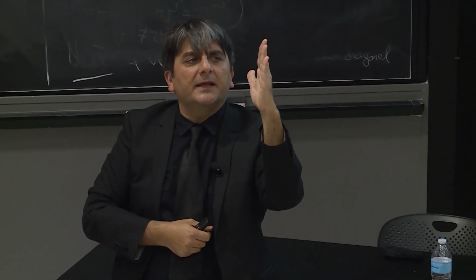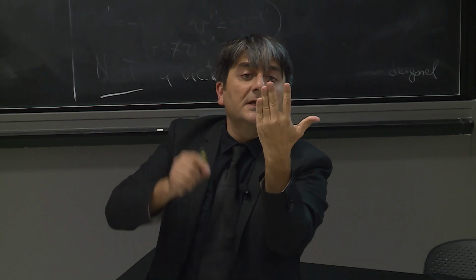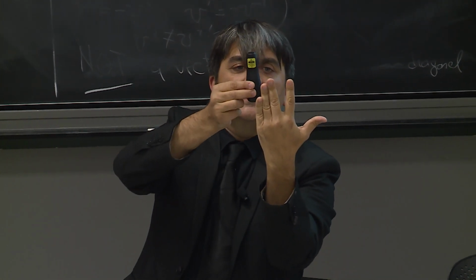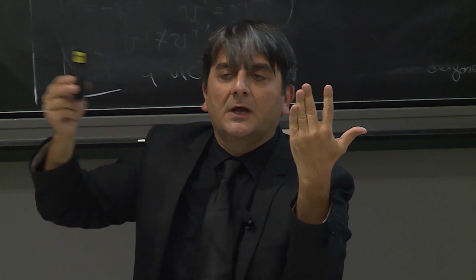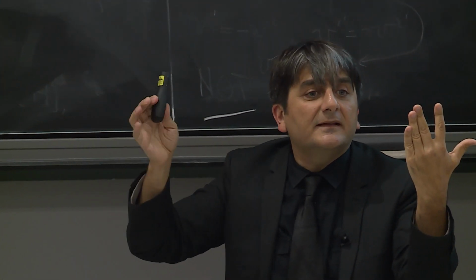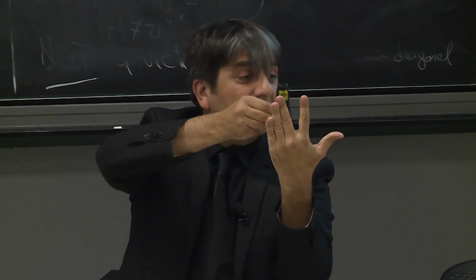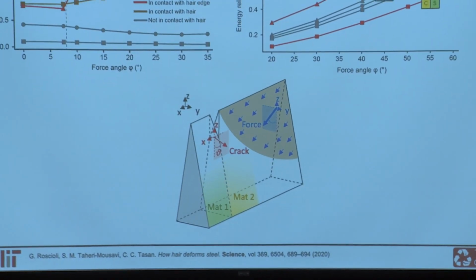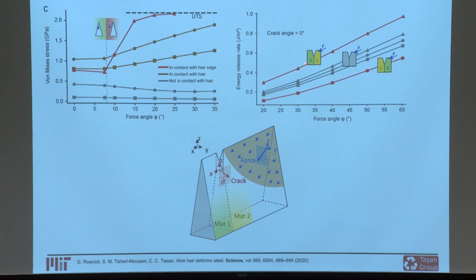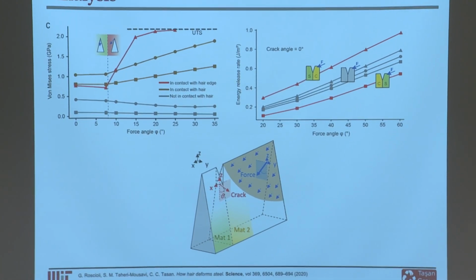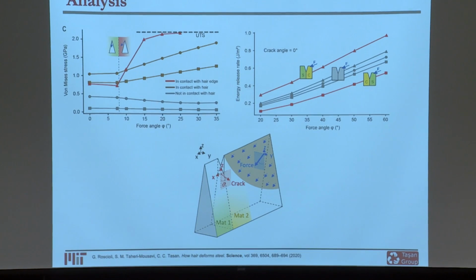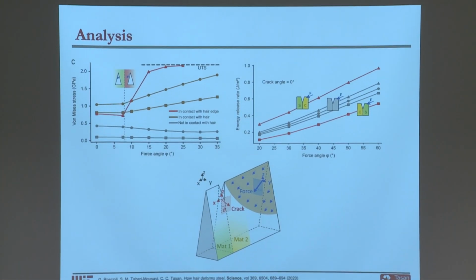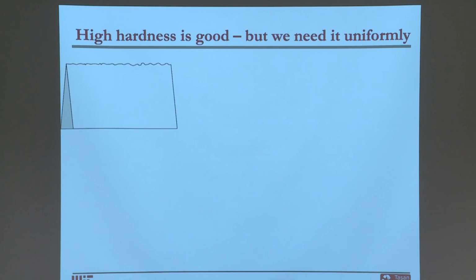And he's also noticed that if you think of my hand as the blade, and if you think of this opening as the notch here, it's very important where the hair is hitting. If the hair is sitting exactly on the notch, or if the hair is sitting very far away, it's not that critical. But apparently, if the hair is really hitting just next to the notch, it becomes the most critical situation. And further, he's also realized that one of the most critical aspects is having a heterogeneity in the material. If you have this notch between a compliant region and a stiff region, it actually becomes much more likely that you'll find regions where crack growth is going to take place.